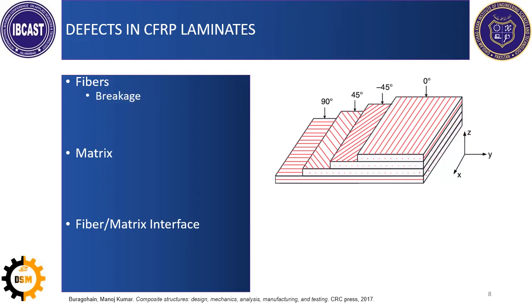So the first defect is the breakage. So the fibers may break. So if you have a fiber here and a fiber here and a fiber here, this breaking of fibers is decreasing the strength of that composite in that specific orientation, and it is dangerous. Another type of defect is the waviness. Waviness means that the ideal situation is like this, but if you have fibers like this within the composite material, these are defects of fibers. So these will affect the functionality of your CFRP structure.